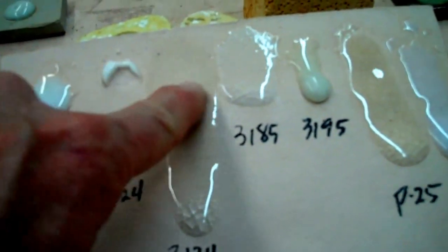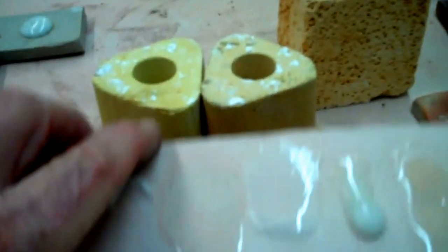You could also melt frit. The thing about frit is they melt much lower. Like this melts at, I fire this at 1900 degrees Fahrenheit. So what I did was I put a scoop up here of each ingredient. And then I set it up on a stilt to fire. So a lot of times what I'll do is I'll take my pencil and I'll write down what I'm supposed to put on there. Then I will come through. And in this case, I may use less of material. So I may just use an eighth of a teaspoon. Put it on there. Then when I put this in the kiln, I'd put about five of them on there. I would set it up like that and then fire it and that would allow it to run.